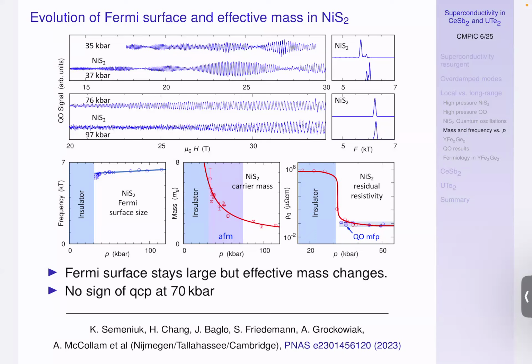And so it's because there's no quantum critical point at about 70 kilobar. Maybe we should look again. But the point I'm making is there's no obvious signature in the mass at 70 kilobar. I mean, there may be, we don't have that much resolution. These are really tricky measurements. There may be a little bump, but the overwhelming effect here is this rise. So I regard the band mass as arising fundamentally from the local interactions, which is the Coulomb repulsion in the Mott insulator. And that provides the baseline band mass, the narrow bands. On top of that, you then have correlations in long-range interactions. They will induce magnetic transitions. They will induce corrections and really interesting things like superconductivity. But on a scale like this experiment, you may not even see that.